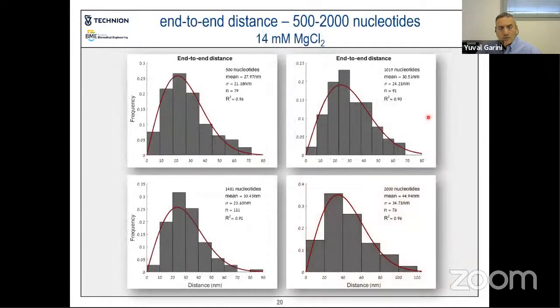And then, of course, we measured the distribution of the end-to-end distance. We had 4 different structures that have a different number of nucleotides, so a different length. You can see all of them. And then what we did, we know exactly what should be this distribution in 2 dimensions. It should be a Rayleigh function according to the persistence length after getting rid of the parts that are taking part in the stem loops. And you can see here the best fit of the Rayleigh function for each one of those structures.